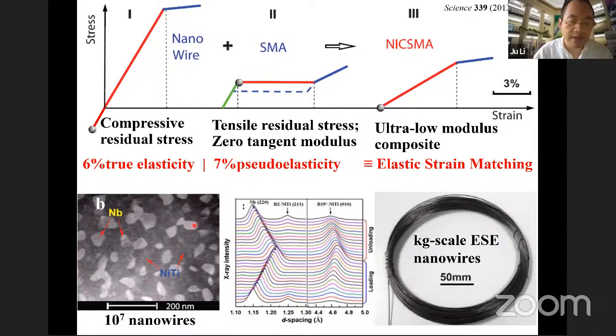The reason is at the atomic scale, if you have a dislocation slip, you have the Burgers vector divided by the lattice spacing, which is more than 100%. So when a dislocation hits this interface, at the atomic scale, it's a very sharp knife, and that very easily destroys the true plasticity of the niobium.